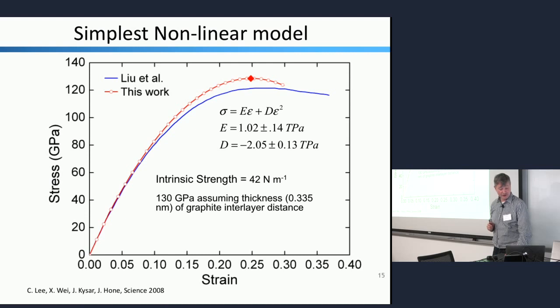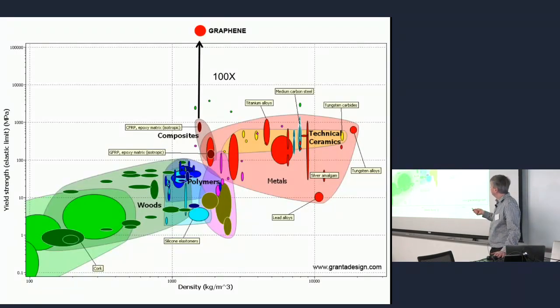Just as a fun diversion, what does this value mean, 100 and something gigapascals for strength? Here's the Ashby plot of strength as a function of density for a whole bunch of engineering materials. Wood is light but not so strong. You get to ceramics and composites. Graphene is up here. I like showing this because it is literally off the chart. It's about 100 times stronger than steel. It's a pretty amazing material, both because the carbon-carbon bond is so strong, but also because we're looking at a material at its intrinsic fracture strength rather than fracture due to defects, which is the case for all of these other materials.